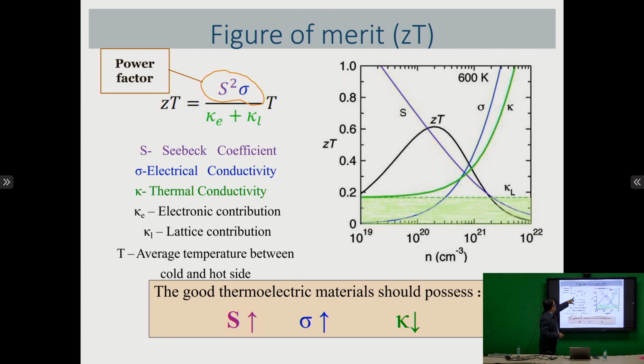Then again, the electronic thermal conductivity: if you increase the electrons there, there are too many electrons to carry the heat from one side to the other side, so thermal conductivity will also increase. So they are connected to each other, and you have to find a balanced position. From this figure you can see that as you increase the carrier concentration of the material, S is decreasing, sigma is increasing, and this is also increasing, but this is decreasing. So somewhere here you will find the ZT is high. You have to somehow tune the carrier concentration and other things to get the higher ZT.